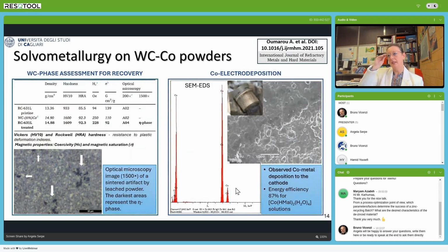residual on the surface. And as you can see in this table, we made a comparison of the properties of the pristine material and the treated material, and also with a reference 6% cobalt powder obtained from raw materials, and we found that the characteristics of hardness and density and the magnetic properties of the materials obtained by recycling were completely in line with the ones of the reference material. We found a lower amount of carbon with respect to the desired one.